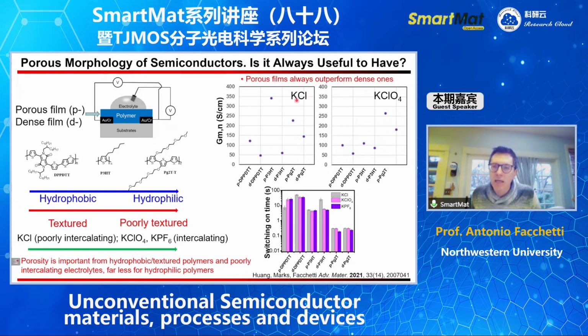But you see here, when the electrolyte is poorly intercalating, the variation is very, very large for the hydrophobic polymers. Instead, when you use the highly intercalating electrolyte, the variation for the hydrophobic polymers is much less. For the hydrophilic polymers, the variation is insensitive to the quality of the electrolyte. This type of behavior is also reflected in the switching time of the devices. There is a big variation when you use KCl, and almost negligible variation when you use the highly intercalating anion.